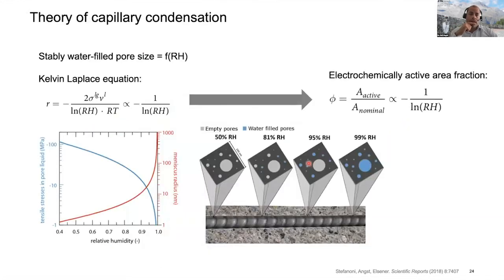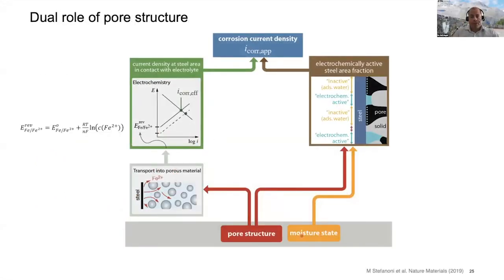This can be quantified by using the theory of capillary condensation, which is a theory that essentially relates the radius of stably water-filled pores to the relative humidity, and that can be used to quantify the electrochemically active surface area fraction. So it is the pore structure at the very interface, together with the exposure moisture condition, that determines this surface area on which corrosion occurs. And that is just an area effect that plays into the apparent overall corrosion current density.